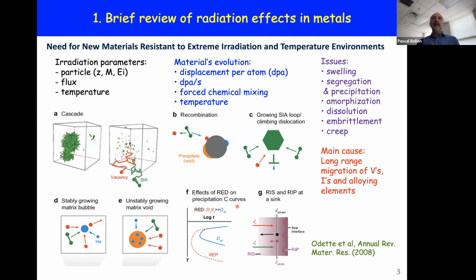And in addition, and it's going to be relevant to part of the talk here, radiation sets up permanent fluxes in these irradiated microstructures. And the reason is that defects are produced homogeneously, but they are eliminated at localized sinks, such as grain boundaries or dislocation lines. And so under steady stationary irradiation, there are permanent defect fluxes, from the homogeneous production within the grains to the elimination of these point defects on sinks.